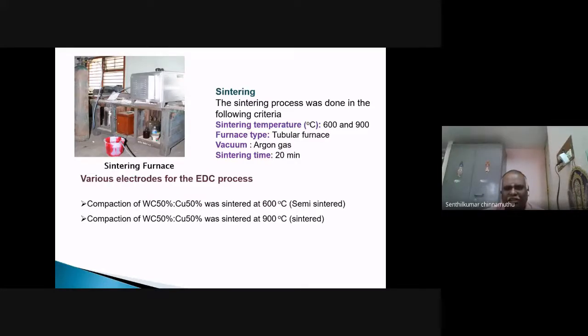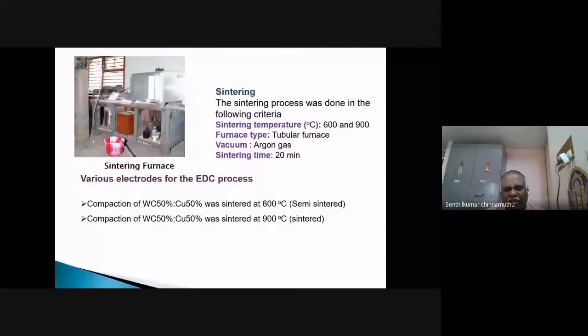The sintering temperature for semi-sintered is around 600 degrees Celsius. For semi-sintering, we have to go for 600 degrees Celsius for 20 minutes sintering time. And for sintering, we have to go for 900 degrees Celsius, 20 minutes for full sintering. So, for the 50-50 combination of tungsten carbide and copper, semi-sintered, you keep the temperature at 600 degrees Celsius for 20 minutes, and sintered, you keep the component inside the furnace at 900 degrees Celsius.